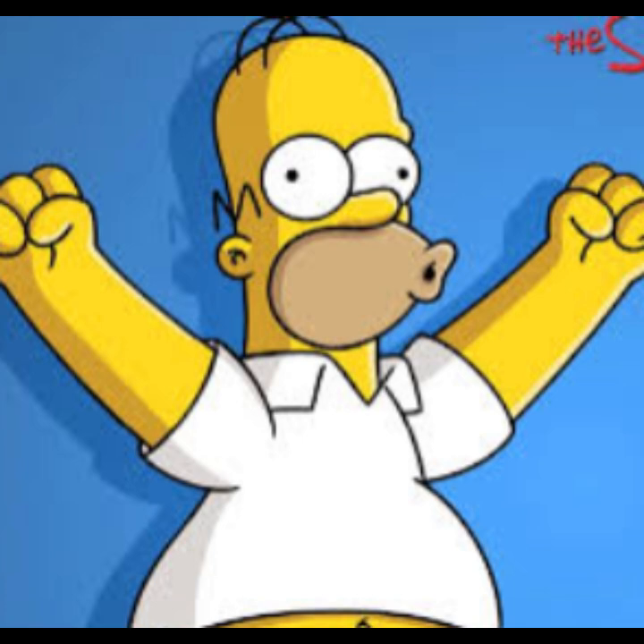There's some really nice TEM here that we did in collaboration with the Sorby Centre, and what we see is that we get this nice systematic repeating of these unit cells. If I zoom in here, you've got lattice fringes that are really quite resolvable, and you can measure these directly. This corresponds to doubling the unit cell from cronstedtite 2M to cronstedtite 4M, and you can see that reflected in the diffraction as well.